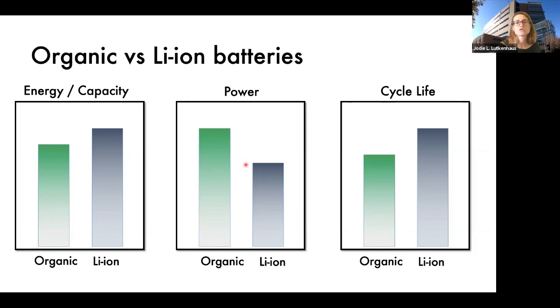In terms of power, the electron transfer is so rapid for these organic chemistries that we can achieve quite high powers. Because lithium-ion intercalation materials tend to be limited by lithium-ion diffusion, which is less of an issue for organics. For cycle life, for the materials I'm thinking of, they tend to not have the same level. They have good cycle life, but I think, in my opinion, it's not quite competitive with lithium-ion batteries yet. And we're going to talk about that quite a bit in the following presentation. The main reason so far is dissolution. A lot of these materials that look so promising will dissolve when you use them, and that leads to capacity fade, and that is unacceptable.